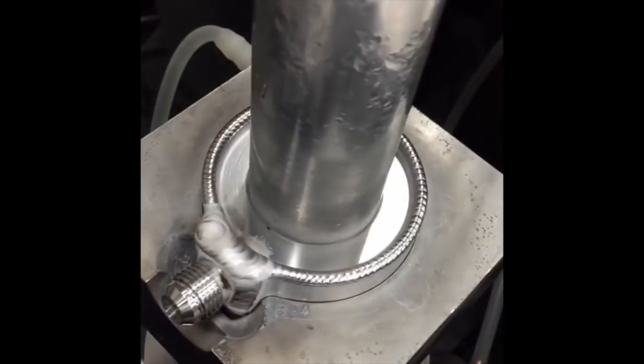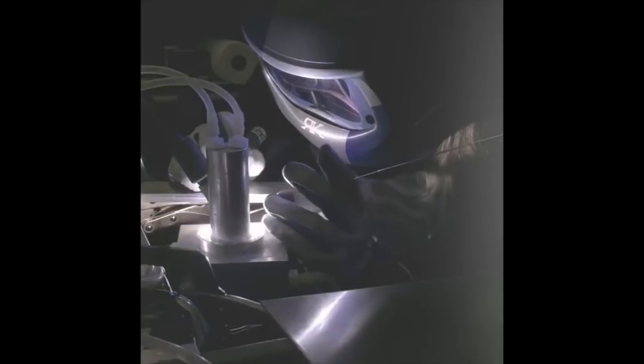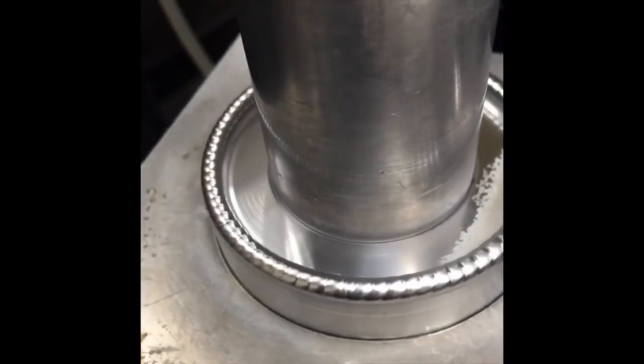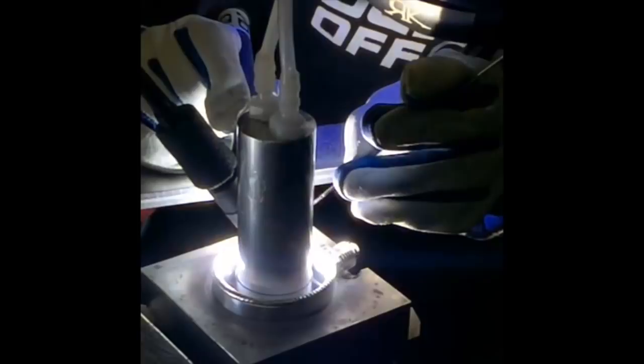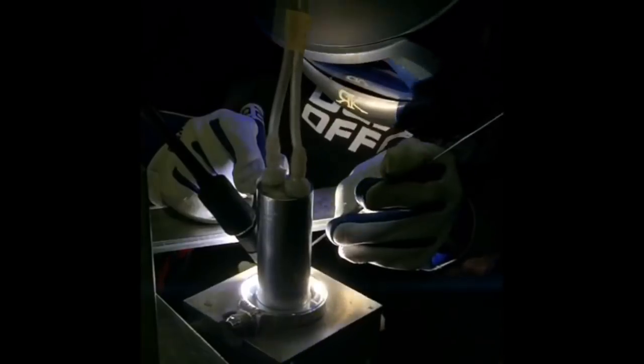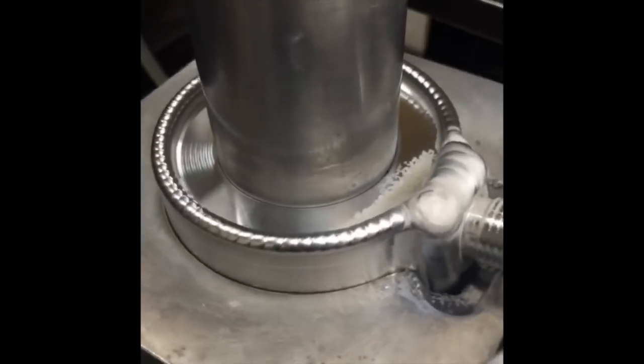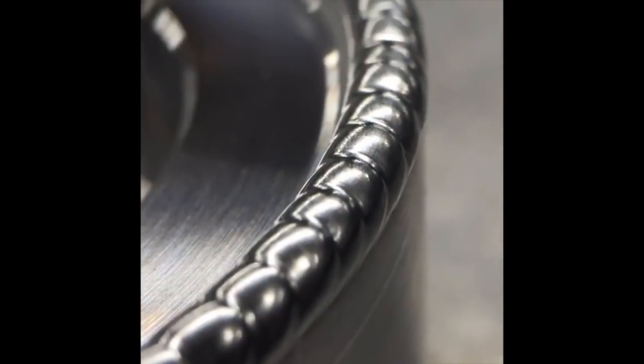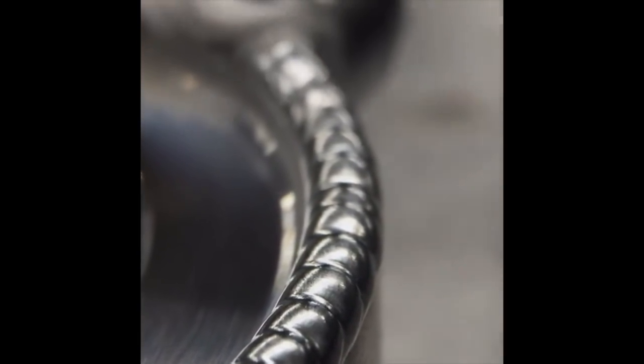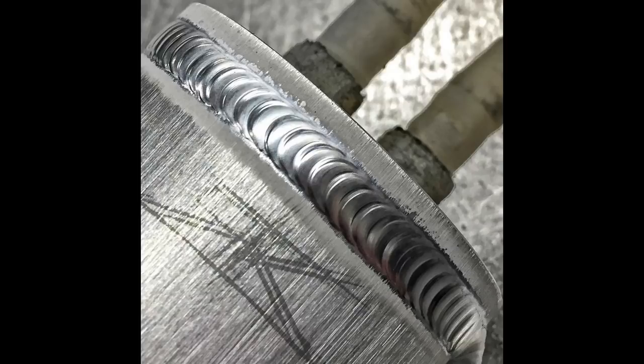Now I've used Blue Shield, which is 95 argon 5 hydrogen, for welding stainless. And one thing I noticed with that is it throws a really big flame off the end of the arc. You get that same flame that comes off of that with the active gas? Yeah, I noticed that when I was doing a recording and I was burning my hand. After I looked at the recording, I saw about a 3 to 4 inch flame shooting out of the end of my torch. Yeah, they'll get you too. You don't see it when you're welding, but boy, you can feel it. Oh yeah. There's something about mixing hydrogen and argon that just doesn't sound right. Yeah, no, it doesn't. I've done the same thing.